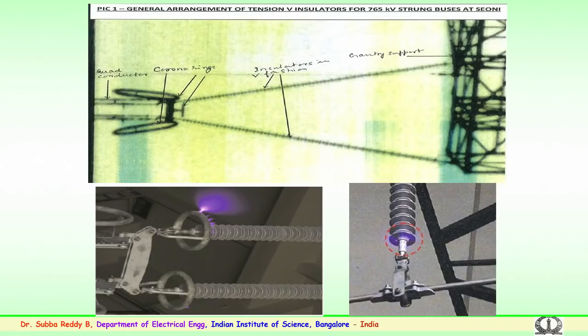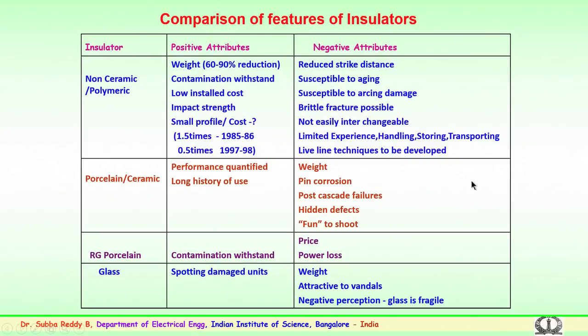And as I mentioned, in case of the fiberglass rod, during the mechanical fixing of the end fittings, if there are micro structural damages, water seepage or the radiation from this UV and continuous corona could lead to the degradation, and the line gets detached. So, these are some of the practical failures which have been noticed in the field.